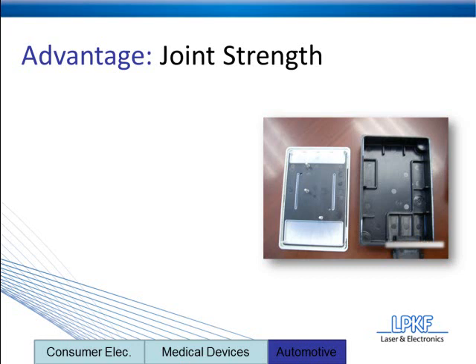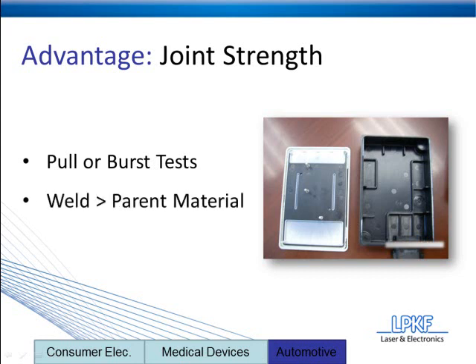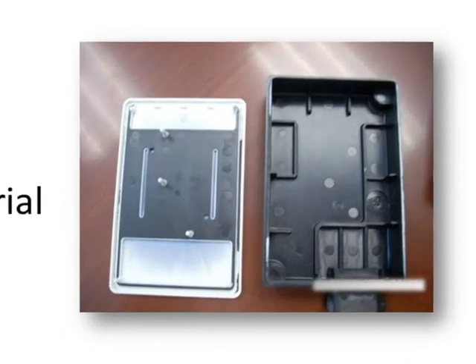The purpose of this slide is to prove that laser plastic welding can produce very strong joints. So in order to do this, we're going to use what's called a pull or a burst test. In this particular instance, a pull test was used. And what we're trying to determine by this test is whether or not the weld is weaker than, as strong as, or stronger than the parent material. Now, in laser plastic welding, you'll find that most of the time the weld will actually be stronger than the parent material. However, let's zoom in and find out for ourselves.